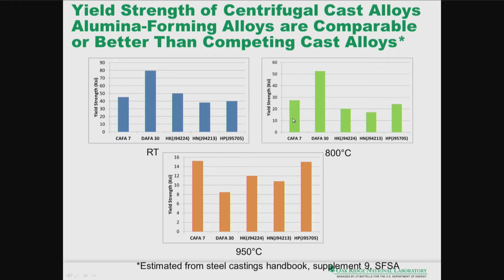As you bump up in temperature, of course, all the strength levels drop. The highest here is 60 KSI, for example. And you can still see that the CAFA 7 is starting to assert itself again, and the DAFA 30 definitely has much better strength properties at 800C. And going up to 950C, the CAFA 7 really starts to hold its own, and as you can see, the DAFA 30 has now significantly dropped in strength, and this is directly related to the fact that the strengthening precipitate is disappearing at these higher temperatures. So in terms of strength, in the DAFA 30, we are limited to temperatures of about 900 or so, which is also consistent with the oxidation performance.